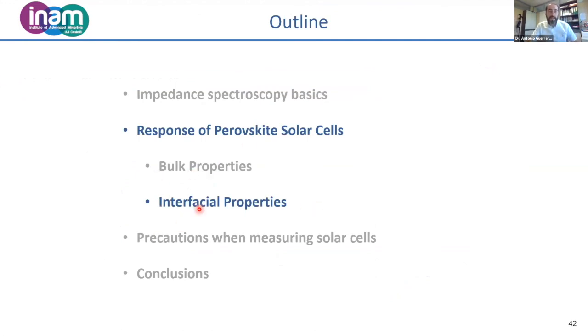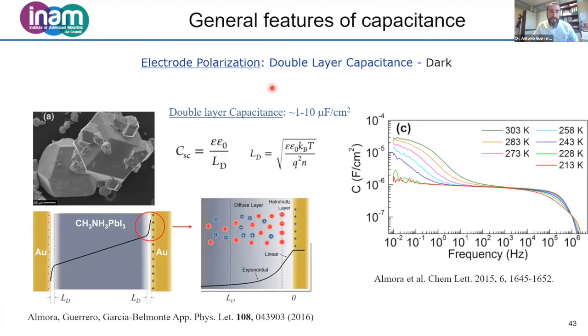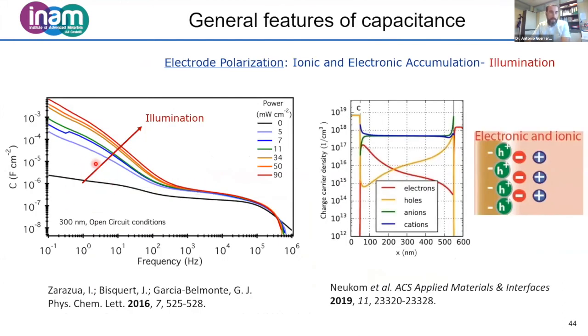So I want to check the interfacial properties. Basically, I mentioned already the double layer capacitance, so there's no need to go into much detail here. But at the time when we published these results, we were surprised to be able to apply electrical models typically used for liquids to devices that are prepared in the solid state. And this is because the perovskite is a very good ionic conductor. When we illuminate, we observe the electrode polarization. Some modeling results like this from Martin Neukom and those shown previously by Uli clearly show the mixed electronic and ionic nature of the interface.